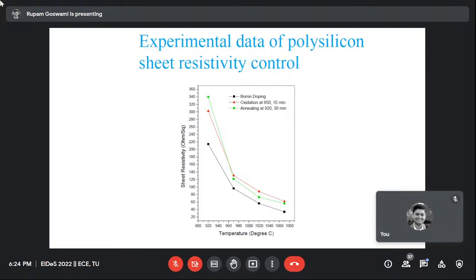Of course, because the process is done here, some deviation from the exact value will be more in comparison to the SOI wafer, because there everything is done in the in situ chamber where the basic growth of the silicon material is done. So there everything is in a much more controlled way, and the required resistivity can be obtained very well. But this is the route where we can tune, and then we can have different performance of the device also, because of this technological aspect of the sensing film. Next, please.